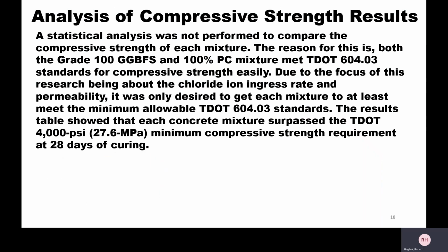So we'll look at the statistical analysis of our compressive strength results. It was not performed because both the grade 100 GGBFS and the 100% PC mix met the TDOT 604.03 standard for compressive strength easily. And again, since the focus of this research is the chloride ion ingress rate and permeability, it was only desired to get each mix to at least meet the minimum allowable TDOT specs for compressive strength. So the results showed that each concrete mix surpassed this 4,000 PSI minimum at 28 days of curing.